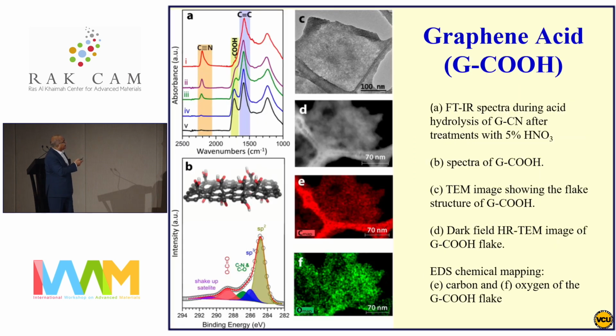And you make graphene cyanide. This is a TEM picture of a graphene cyanide flake. You make this actually from fluorinated graphite with potassium cyanide. Reflux over, you can form graphene cyanide. And you can see clearly the CN band in the FTIR, characteristic of the graphene cyanide.